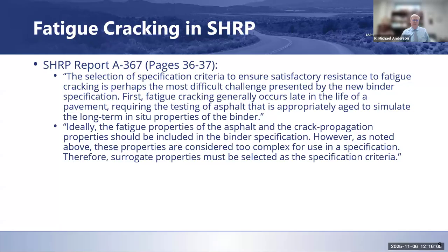Then they also talk about ideally that those properties include crack propagation properties as well, and then noted that those are considered to be too complex for use in a specification, and surrogate properties must be selected as the specification criteria. So if you look at fatigue cracking, what they generally do is break it down into initiation of the crack and then propagation of the crack. So part of it is getting the crack to start, and then how does that crack progress? They felt like putting both of those together was a little bit too complicated, perhaps, but if they use surrogate properties, they could relate to those.